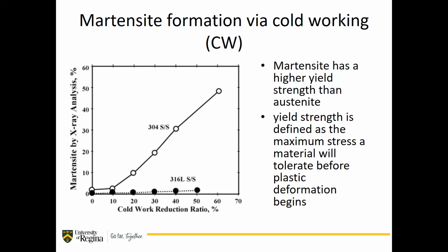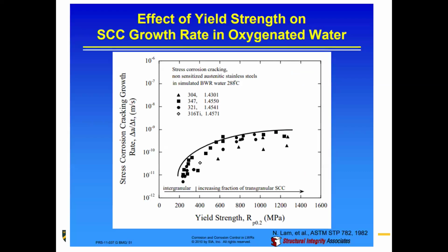And we'll talk about why martensite starts to create problems when it comes to carbon. We're going to get to that in a sec. It's the next slide. So what I'm showing you here is yield stress versus your stress corrosion cracking growth. Importantly, this is not necessarily intergranular. This is just stress corrosion cracking in general. And what can happen is if you have a very high amount of yield stress, usually again due to martensite buildup within your steel, you can actually get transgranular stress corrosion cracking. So cracking right through the actual grains themselves, because this ends up being susceptible to SCC.